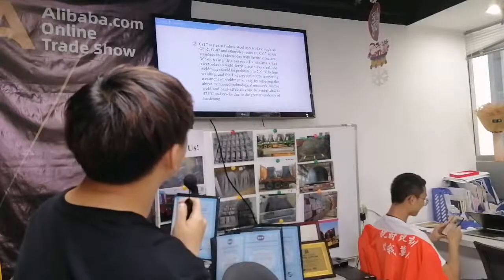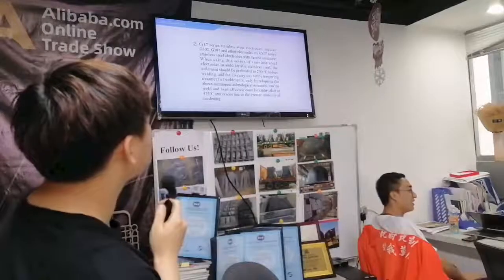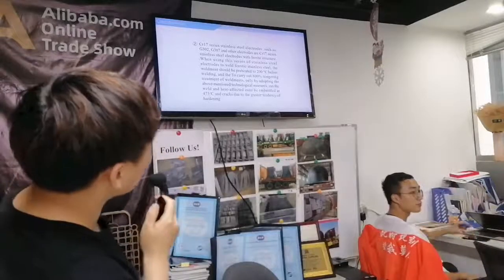The second one is CR17 series stainless steel electrodes such as G302, G307, and other electrodes are CR17 series stainless steel electrodes with ferrite structure. When using this series of stainless steel electrodes to weld ferritic stainless steel, the weldment should be preheated to 200 degrees before welding, and 800 degrees tempering treatment of weldments should be carried out.